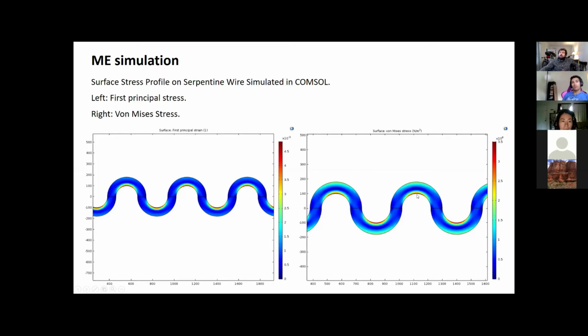wire thicker, wider than this part, just to have more room for the parts that get damaged over time, so that the overall width that electrically passes current wouldn't really get affected as much, because the less wide this gets, the more the resistance overall is going to go up. So you want a wider part here. That's what I learned from the mechanical simulations. And let me get us to the fabrication steps real quick.